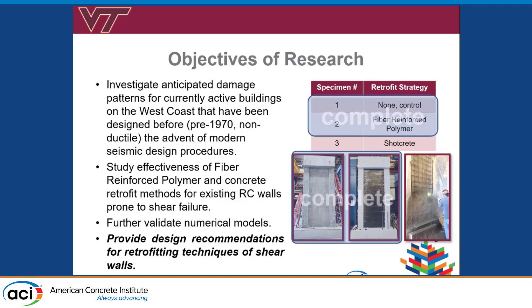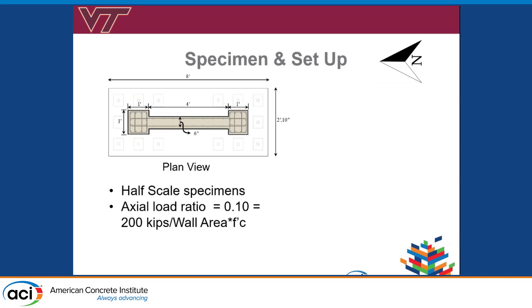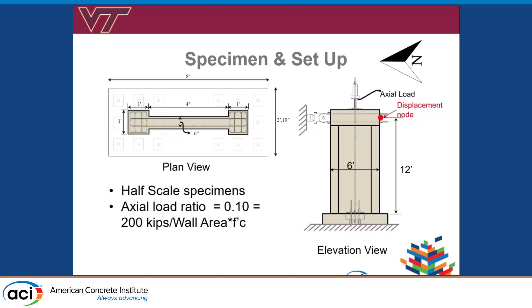I've completed the testing for the first two specimens — the control and our FRP — and we're in the process of testing the shotcrete. The specimen we built is a six-inch-thick web, four feet wide, with a vertical reinforcement ratio in the web of 0.25% — very light. The pilasters, these end column regions, have vertical reinforcement ratios of 3%. We applied an axial load of 200 kips, a ratio of 0.1. The displacement measurement is at the top of the 12-foot-tall wall, and this is a half-scale specimen.